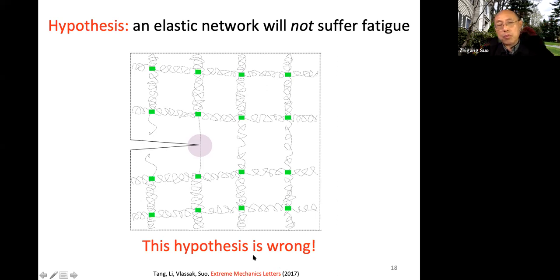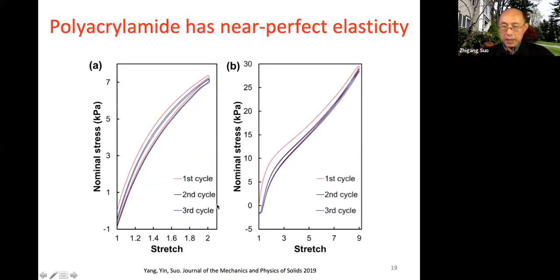My hypothesis was wrong, and this material suffers fatigue. Let me show you the experimental picture. Before I show the picture, I first show you this material is nearly elastic. So we stretch it to double the length, or even 9 times the line length. It's a huge stretch. You can see the hysteresis loop, especially after 1 or 2 loops, the hysteresis is just negligible.